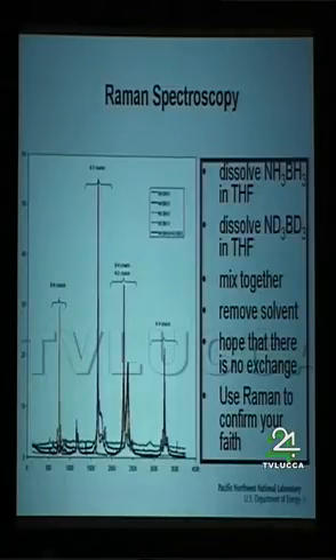So we talked to our Raman spectroscopist, and so she was able to look at the solids of all these materials. And since nitrogen and boron are relatively light elements to begin with, if you put deuterium on there, you can significantly stretch the BD stretch. And so you can look at the Raman spectra of this and get a fingerprint of each one of these species.